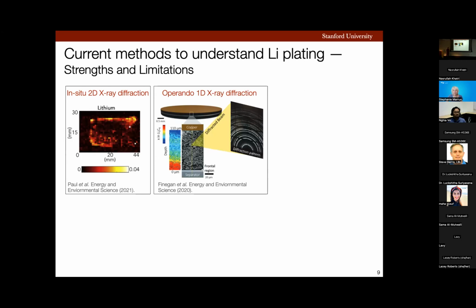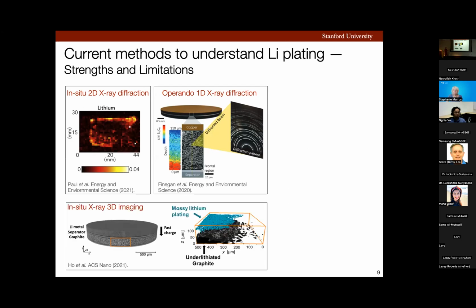and morphological information was missing from both these studies. And that's where the gap was bridged by another study conducted by scientists at UC Berkeley and LBNL, in which they did in situ three-dimensional X-ray imaging to create 3D mapping of lithium plating. And this work showed how this layer of mossy lithium leads to underlithiated graphite particles underneath.